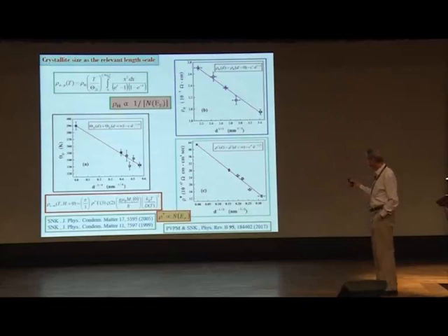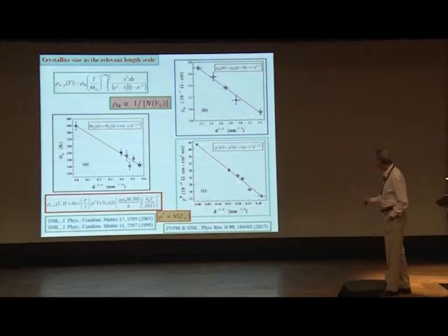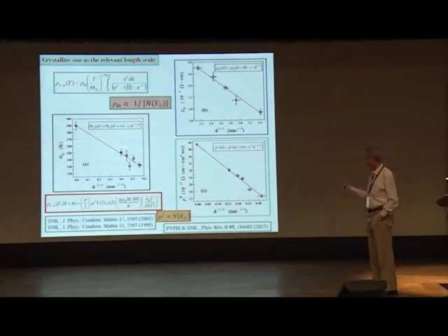That's why they have an inverse relationship, as you can see, where the phonon part is decreasing and this other part is increasing, because I have plotted it as 1 by d, root d. So this is the bulk value, for example. Similarly, this is the bulk value. So one can understand why you should be seeing this trend, why one should increase and the other decrease. But the very fact that, as I said, they go as some powers of the average crystallite size would mean that that is really the controlling length scale.